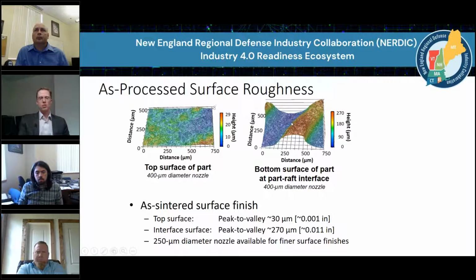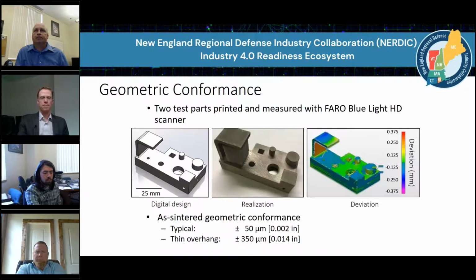So on the top surface, we have roughly 30 microns from peak to valley. On the bottom surface, it was about 270 microns. If I had to guess today, it's probably maybe 170 microns from peak to valley. There is a finer diameter nozzle, 250 microns, that you can use to get a smoother surface finish if desired. You can also do post-processing, so a little bit of treatment either in the as-printed or as-debound state, and you can do some cleanup on the surfaces.